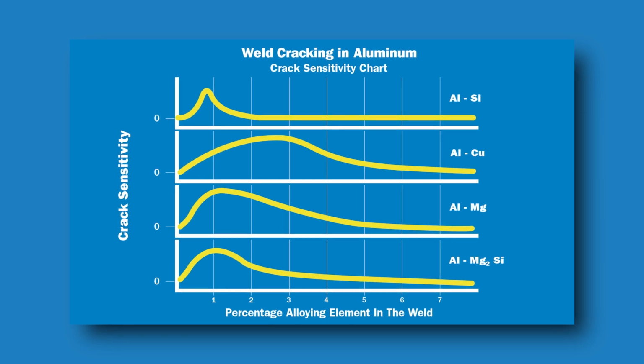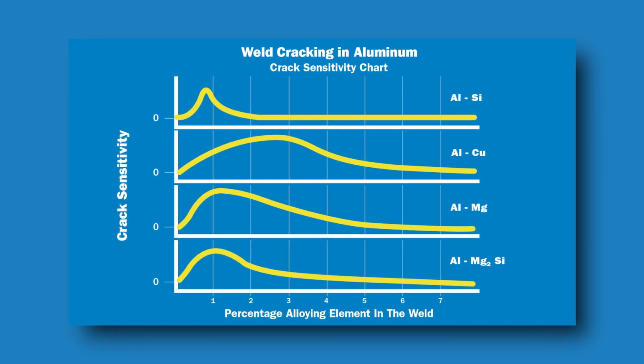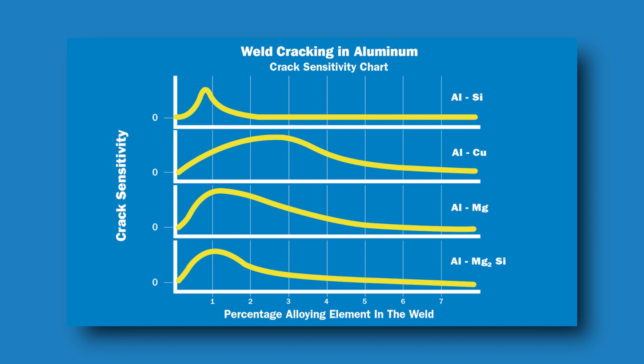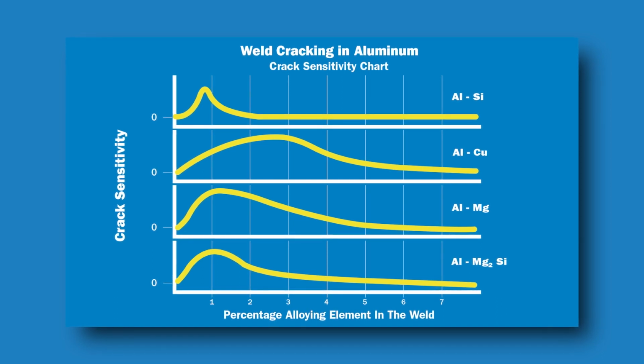As you can see in this chart, when small amounts of common aluminum alloying elements are added to aluminum, the crack sensitivity increases dramatically. This is why common filler metals have high alloy percentages. 4943 and 4043 have between 5 and 6% silicon, and 5356 has between 4.5 and 5.5% magnesium.